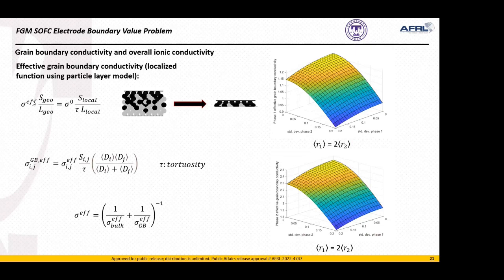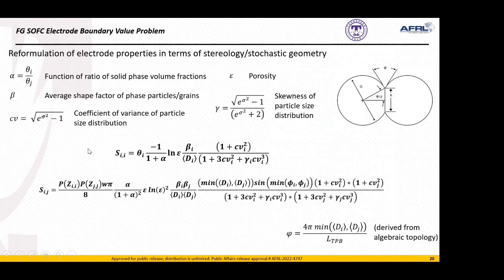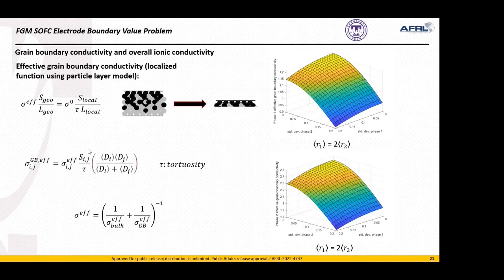Now, we localize the conductivity using a particle layer model. Then the geometric surface area and the geometric length of the electrode are shrunk down to characteristic surface areas and characteristic length scales. The tau here is the tortuosity of the cell. And if empirically someone has defined a grain boundary conductivity of, say, YSZ, which is also oftentimes different than the bulk value, then the geometric addition to that effective conductivity is given by this expression here, where S sub ij is again given by the expression that we already showed before. And then the bulk conductivity and grain boundary conductivity can be defined through the equation on the bottom.